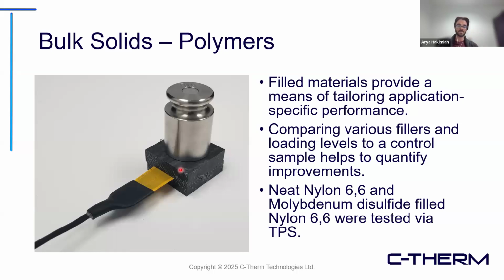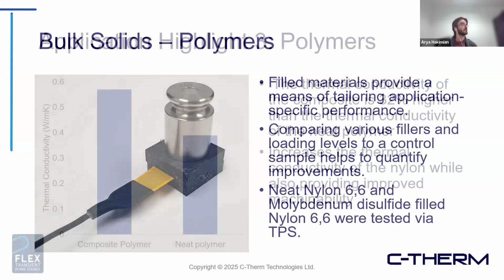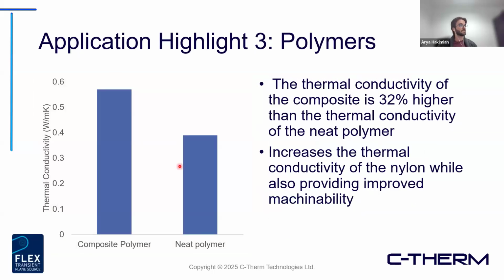These are blocks of samples that were cut. And the data that we'll show here, we're comparing a neat nylon to one that was filled with a conductive material, just again, to do some relative comparisons there. So we can see here that the composite polymer, the one that had that additive, was, of course, as you might expect, demonstrating a higher thermal conductivity than that of just the base material itself.